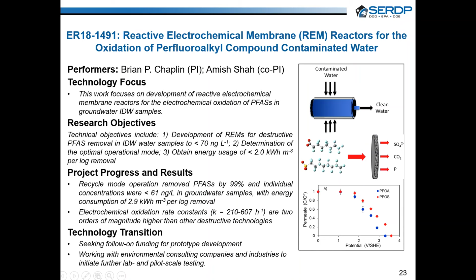Additional work involving real groundwater samples was also conducted. Results showed that single-pass flow-through mode could only achieve approximately 50% PFAS destruction, which was attributed to background organic constituents and low solution conductivity. However, operating in a recycle mode with high permeate fluxes achieved greater than 99% destruction of the total measured PFASs, with individual concentrations less than 61 nanograms per liter. Recycle mode required a total energy consumption of only 2.9 kilowatt hours per cubic meter per log removal, which was significantly lower than other destructive technologies.